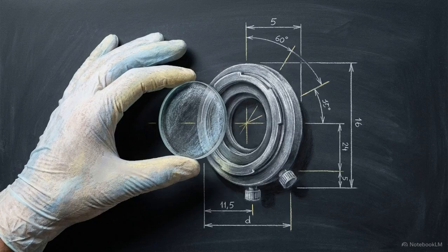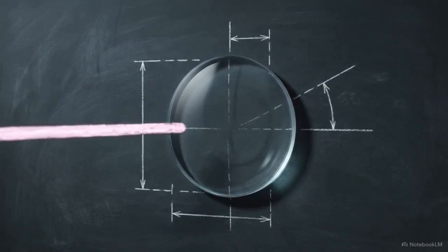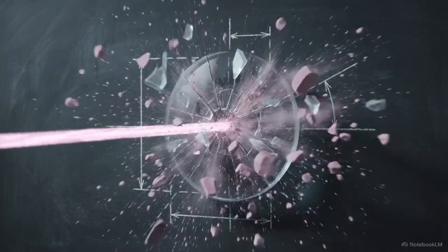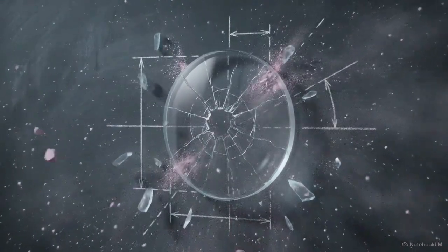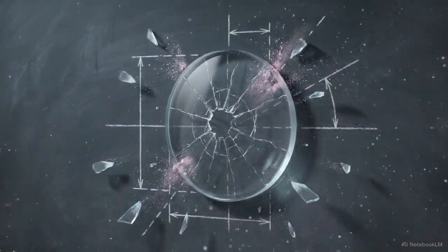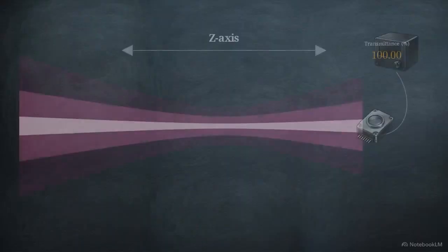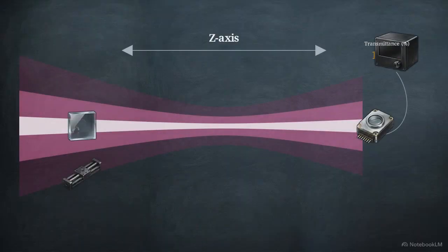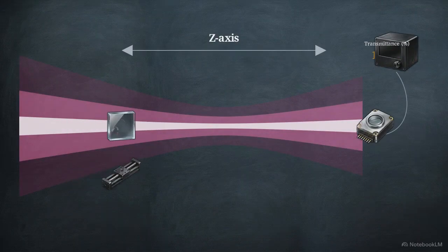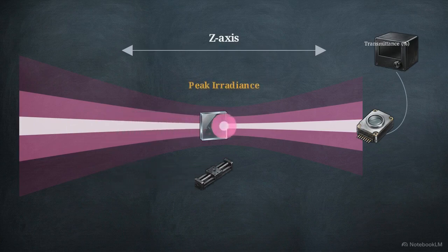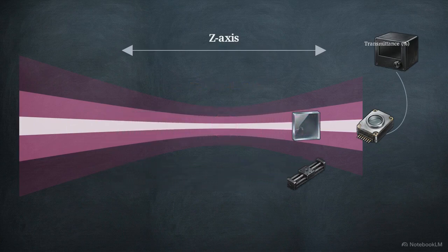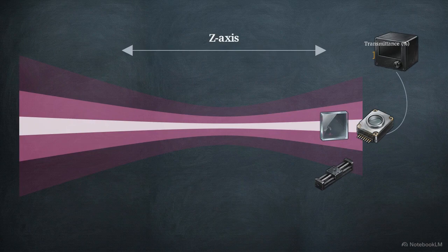If an engineer puts a standard optic into a high-power beamline without accurately quantifying both of these specific parameters, the beam can violently distort, or the optic itself can shatter. The definitive laboratory technique to isolate and measure these two properties is the Z-scan, originally developed by Eric Van Stryland. The method relies on a single precise mechanical action, translating a material sample along the z-axis of a laser beam to map spatial phase distortions directly into measurable changes in light intensity.